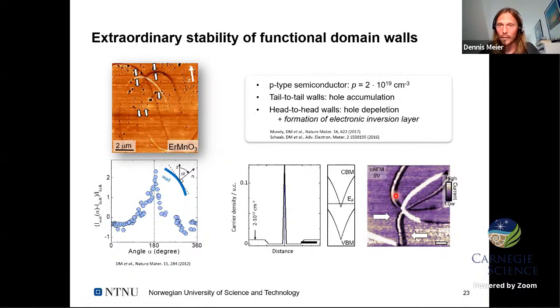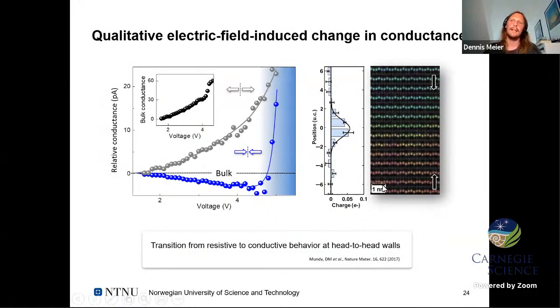Here you have, for example, one of the head-to-head domain walls. First, the conductance goes down, then up in the middle again, and then down. And this already shows a very interesting, unusual electronic signature of these head-to-head domain walls, which we then utilized. You see that these carriers sitting at the head-to-head walls need a certain activation energy. On the left-hand side, these are now IV curves where we measure the conductance at head-to-head walls. They're first insulating all the time, and then when I go above a certain threshold voltage, they become conducting.